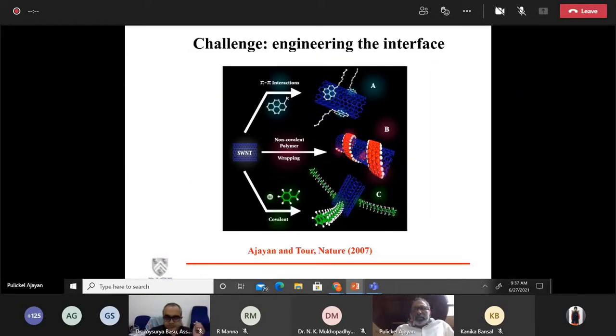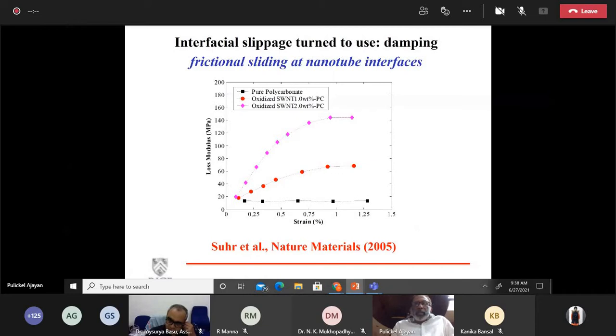When you go to larger and larger systems like composites, the problem becomes quite severe on how you can modify these interfaces so that you can tailor mechanical behavior or electrical behavior. And again, we have done quite a lot of work in understanding how these interfaces can be modified using chemical modifications. The interface really makes a big difference on the overall properties. If you really don't make these proper connections at the interface between the matrix and the nanostructure that is embedded, you can have a lot of mobility at that interface, the frictional sliding, for example.